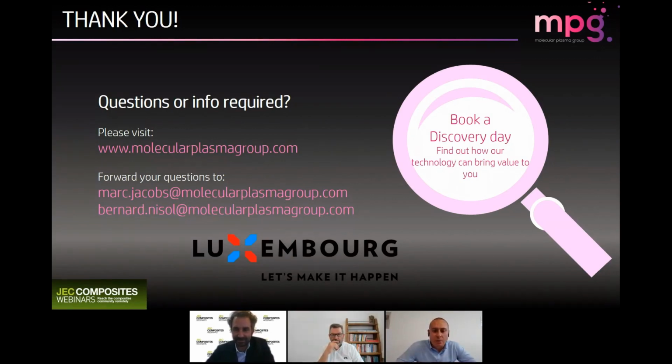In that case, one thing we could do is a two-step treatment. The first step would be an actual plasma activation and cleaning, a bit like the Corona does, but at our range of energy, which would be sufficient to remove the volatile material, after which we would apply our coating. And we have seen that with the coating, which is very different from a surface functionalization with typical Corona, we can actually avoid having the material migrate to the top surface. If there is enough room for grafting with the actual substrate, it won't be a problem.